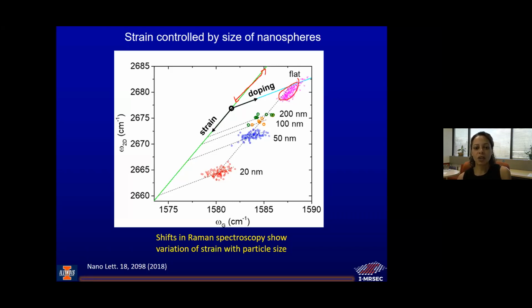Okay, now we go to 200 nanometer graphene, and you can see we're moving just along this line. Okay, so again, moving parallel to strain, which means as we go from flat graphene to graphene on 200 nanometer spheres, it gets strained. Down to 100 nanometer spheres, it gets strained a little more. Down to 50 nanometer spheres, it gets strained a little more. Until we get down to these 20 nanometer spheres, and you can see that we have a very high amount of strain. And in fact, the amount of strain depends on the particle size. So we're controlling strain in these materials.